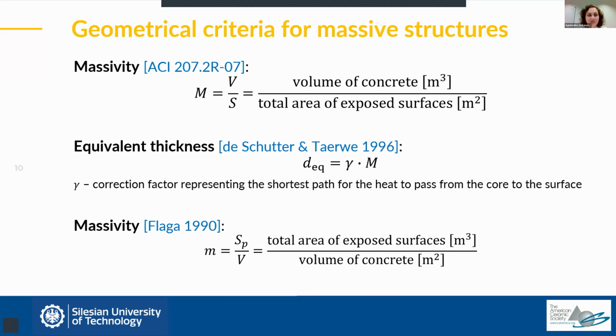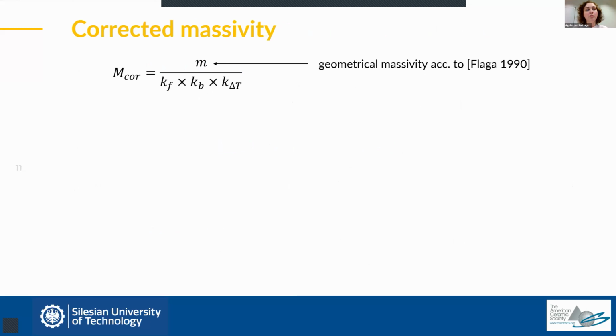And these measures were satisfactory as long as the concrete industry was based on Portland cement. Nevertheless, we know that for many years already, we tend to use mixed cements in our concrete, and therefore it is not enough to just base on geometrical criteria to define the thermal cracking potential of the structure. That is why a working group within a RILEM Technical Committee in which I was involved proposed a corrected massivity, which uses the geometrical massivity, but proposes some correction factors to account for other important factors that influence massivity.